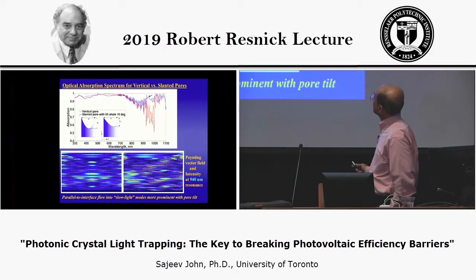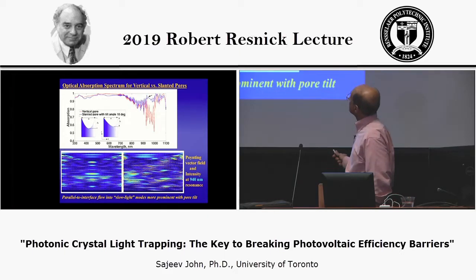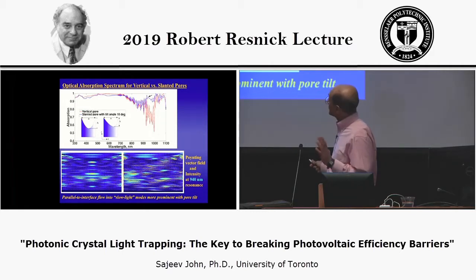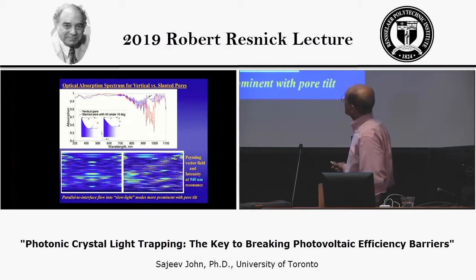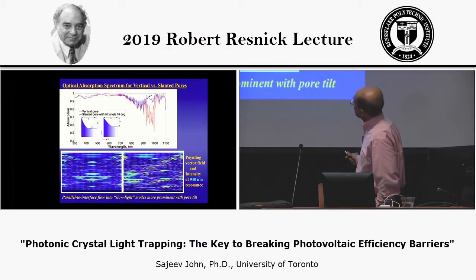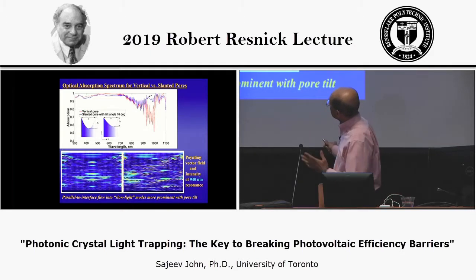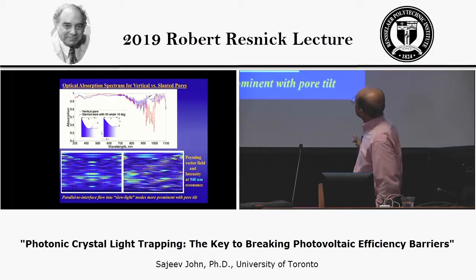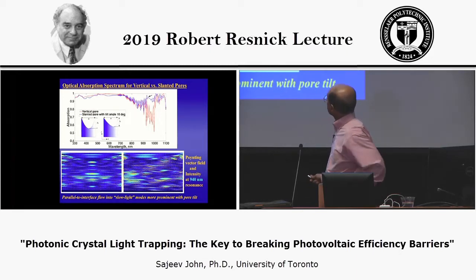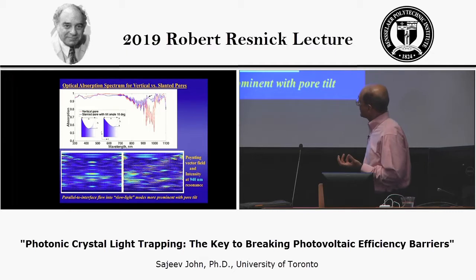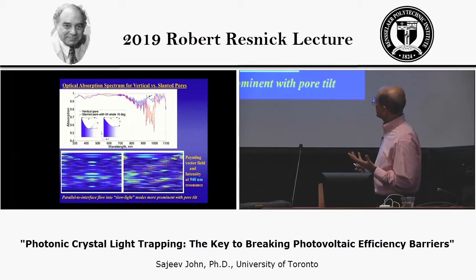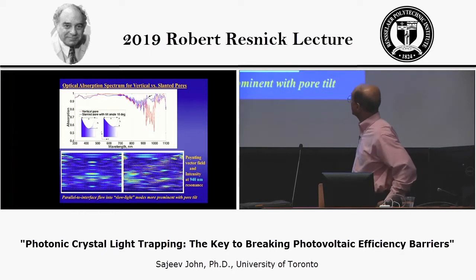Here is a little bit more detail of the optical absorption spectrum that we calculated, not only for the exact parabolic pore structure that Professor Lin's group created, but we also showed that if you were to put a tilt in the orientation of these pores, instead of the red curve, which corresponds to the vertical pore, the absorption could be increased even further. And here's a picture, a snapshot of the electromagnetic field profile. The yellow arrows, which you can barely see, are the Poynting vector, and the colors represent the intensity, red being the highest and blue being the lowest.